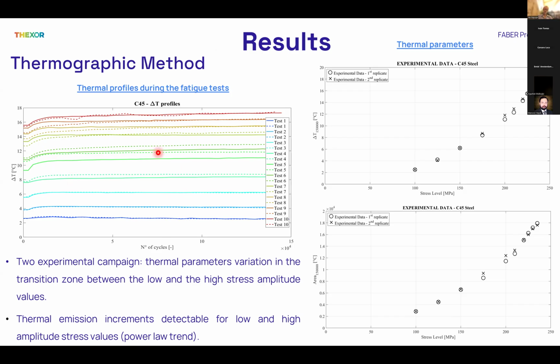The graph on the left side reports the thermal profiles obtained during the fatigue test. The solid line refers to the first experimental campaign, while the dashed line refers to the second experimental campaign. The blue colors report the thermal profiles obtained with low stress amplitude, while the red color refers to the high stress amplitude values adopted during the fatigue test.